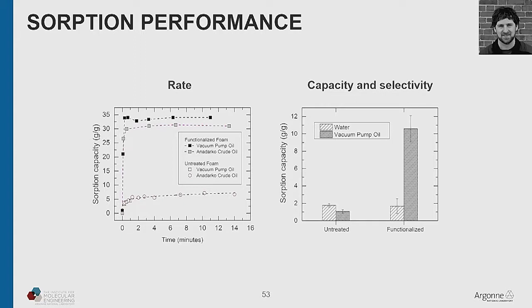It's a very slow process. It'll slowly find its way into the foam. After you do this two-step functionalization with SIS and then the silanization, you can see that you get a huge increase in capacity, more like 30 grams per gram with this particular sponge, and it happens very, very fast, which you'll see shortly in the video. Now that 30 grams per gram is actually fully saturating this sponge. All of the available volume inside those pores is filled with oil.